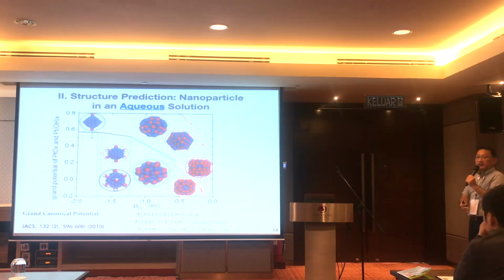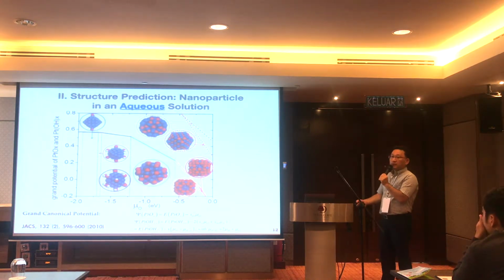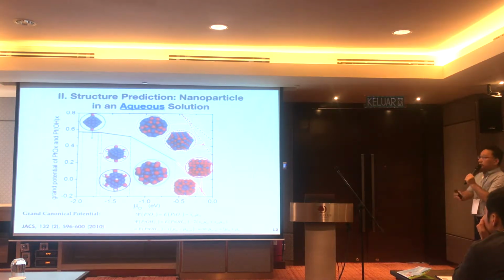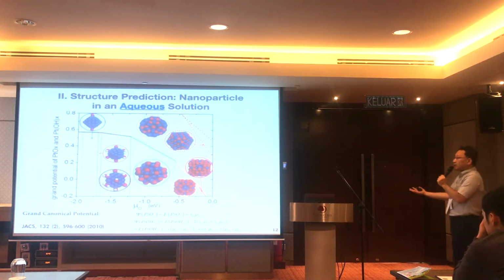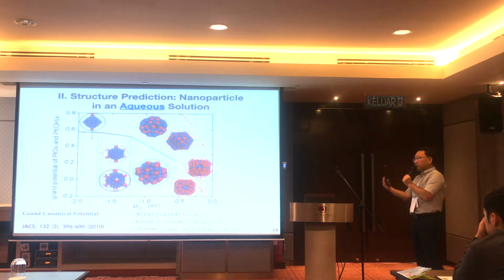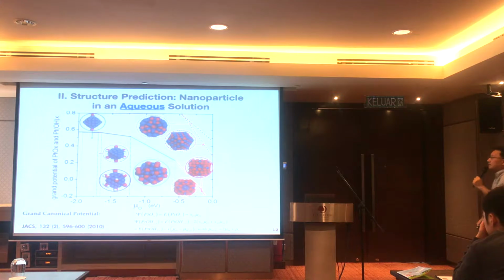That's why you are using platinum as a wedding ring. But in nanoparticle form, platinum does oxidize. Yeah, don't give nanoparticle platinum to your wife. It will be oxidized like that. And even oxygen can propagate or diffuse into the subsurface of platinum nanoparticles. Platinum completely decays, and then you are losing all the properties of platinum.